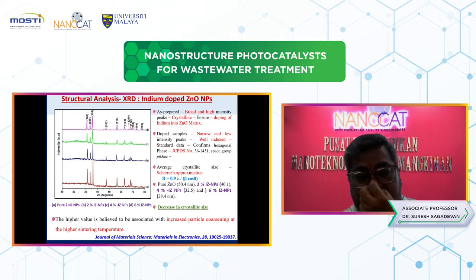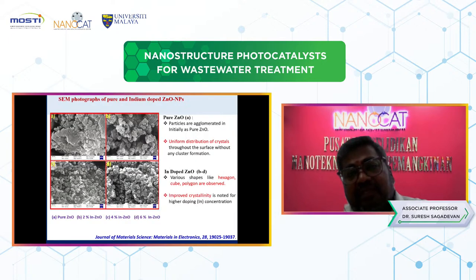Look here, pure zinc oxide we calculated to be 50.4 nanometers, but with increasing doping concentrations the crystalline size decreases. The higher crystalline size is due to the temperature, and this material has the crystal structure confirmed by this XRD analysis. Then the morphologies: you can look at the morphology for A, B, C, D. A represents pure zinc oxide, and B, C, D represent various shapes. Look at how the shape and morphologies change; hexagon, cube, and polygon shapes are observed. Crystallinity is also noted for the higher doping concentration. Figure D is the higher concentration, 6% indium doped zinc oxide.